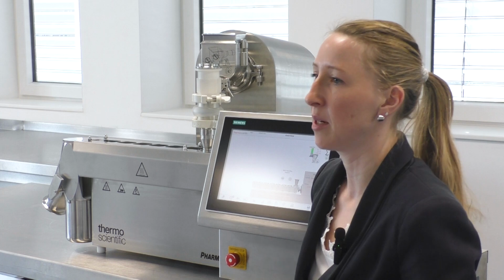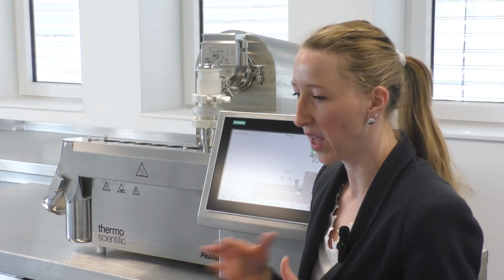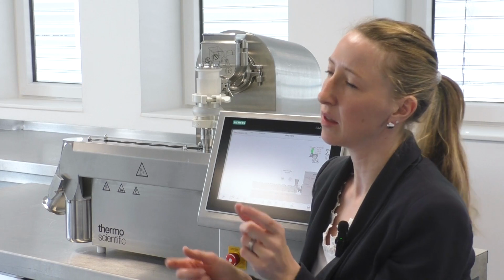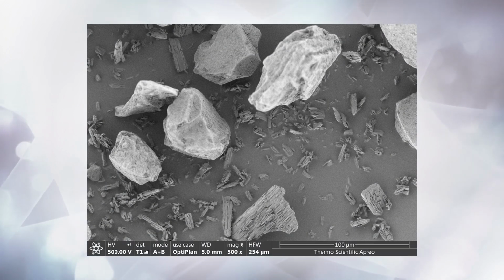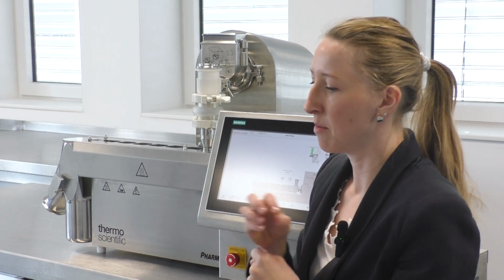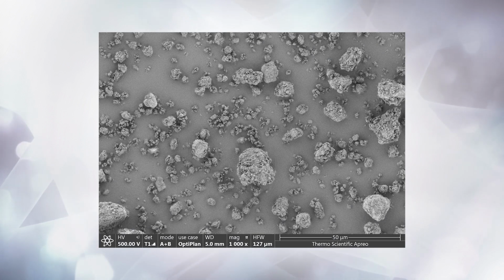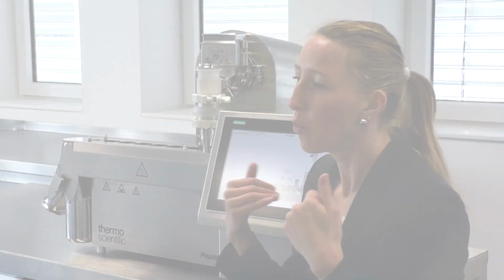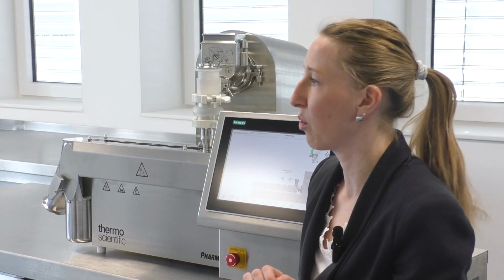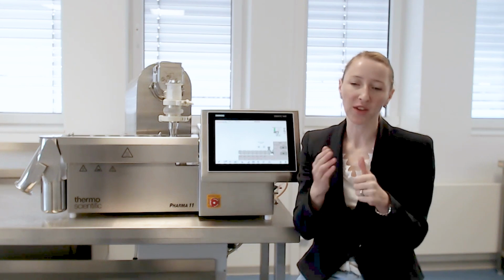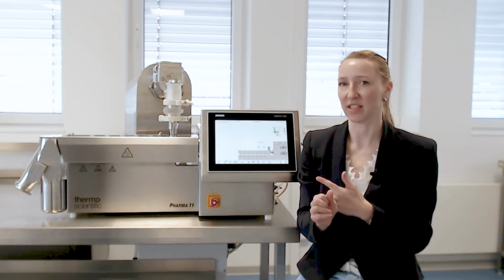In addition, we did a couple of SEM pictures to see how the particles are changing. So you could nicely see when you do this process, the particles get smaller. So we really mill down inside of the extruder. And we could see that the crystals, so the API crystals, got lost after processing. So the crystals really were broken down and got into these pores. A nice proof with DSC, XRD and SEM.